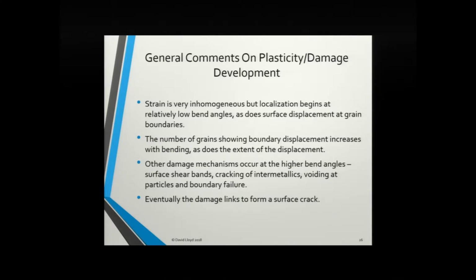So the general comments then, just to recap: the strain is very inhomogeneous, not surprising, localizing begins at relatively low bend angles, and the surface displacement at grain boundaries also comes in at relatively low bend angles. The number of grains showing the boundary displacement increases with bending, as does the extent of the displacement at any particular boundary. Other damage mechanisms occur at higher bend angles.